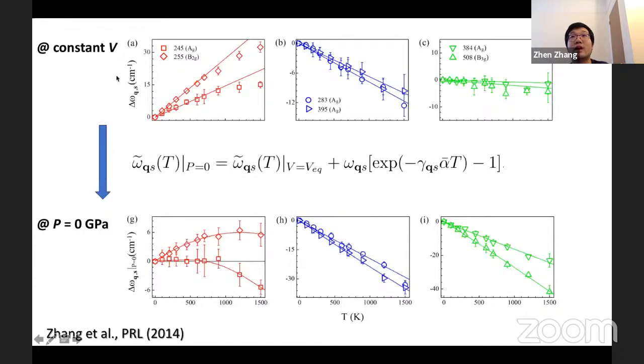So first, renormalized frequencies were obtained at constant volume. Then we use the formulas introduced above to convert omega at constant V to constant P at 0 gigapascal. So for the experimental Raman modes, we successfully reproduced the irregular phonon frequency shifts. Some frequencies remain constant, some increase, and some decrease.